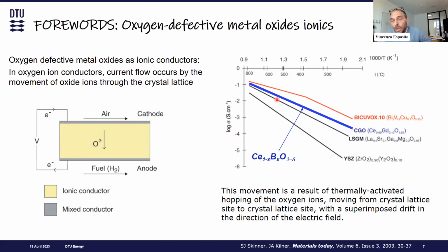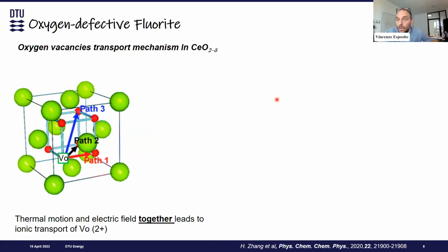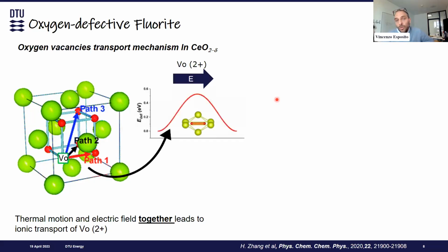If you look a little closer at the structural level, you will see that the oxygen ion transport occurs because there is some exchange in the site position of the oxygen vacancies. And this can happen through different paths, with different activation energies. But the most important condition is that we have enough thermal energy to activate this process. So together with the application of an electric field, we can move these vacancies, or if you look at it from the other side, we can move oxygen from its position to the vacancy place. So we have this transport effect at high temperature.